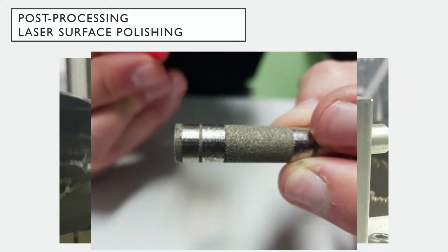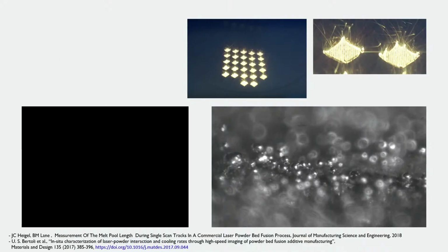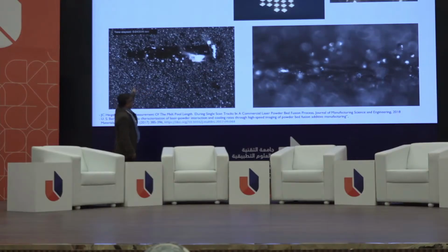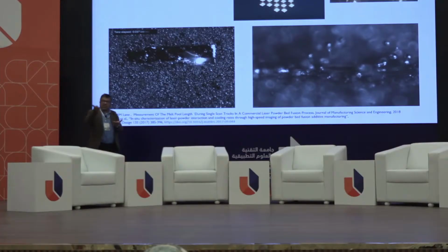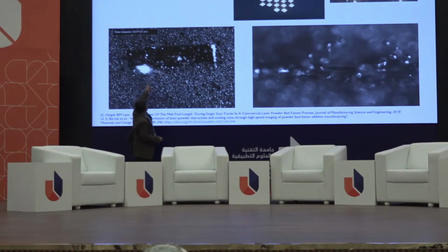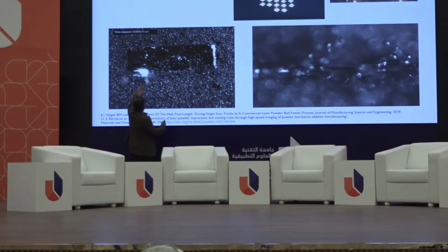Yeah. So this is a high-speed camera, and then the speed was lowered down. When you see this from the top, the laser beam is coming from the top here, from the side. You can see, during the movement of the laser beam, there will be melting and evaporation, so it will generate negative pressure on the top, and this will make turbulence and suck the powder. See here, even this powder before the propagation, most of this powder is pushed upward.